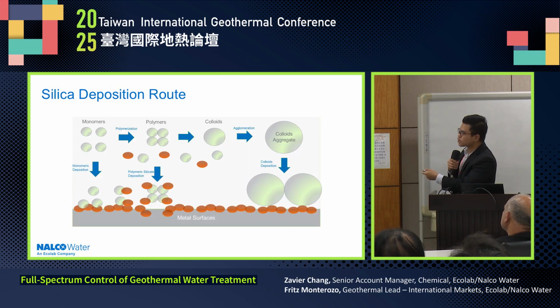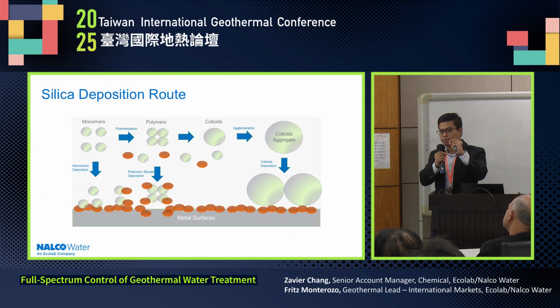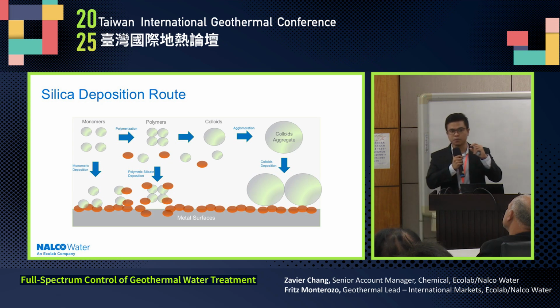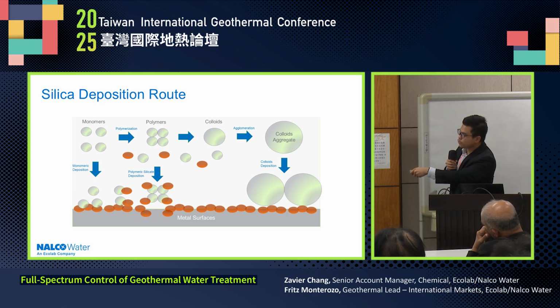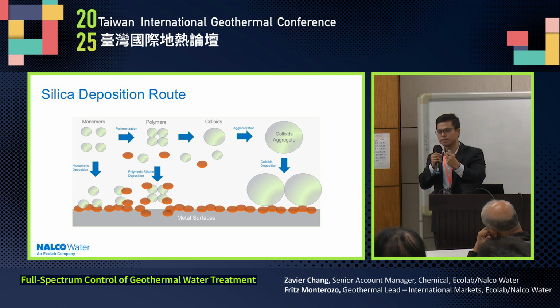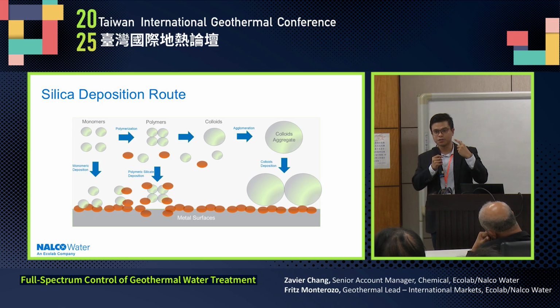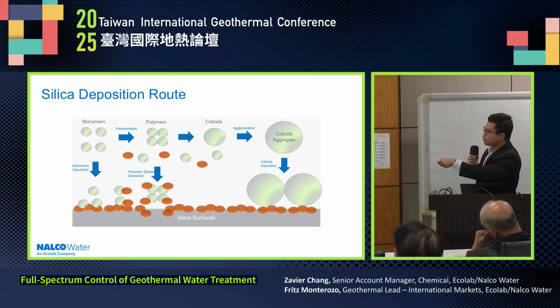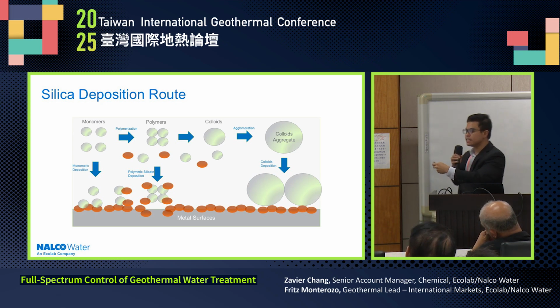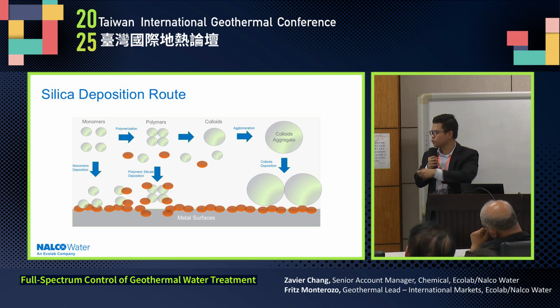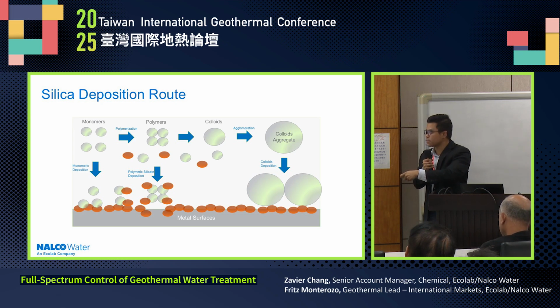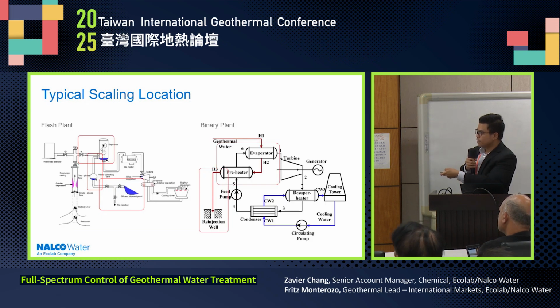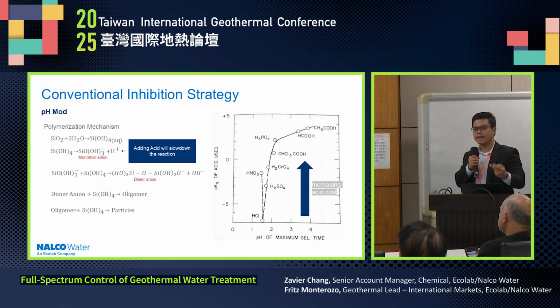So how does silica deposit? The way silica deposits, we call it polymerization. It starts with monomers, silicic acid monomers. It will form into polymers, and then it will grow and grow until you have silica colloids. This is still not visible to the naked eye. Then these colloids will aggregate, and once it is heavy enough, it will drop out of the solution, forming your scales.